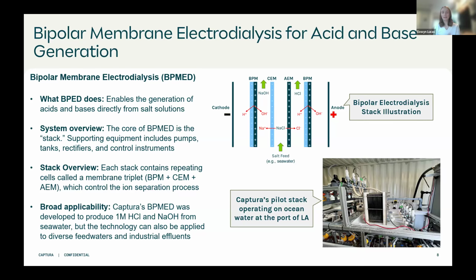So the image on the bottom here is an example of one of our pilot stacks that's currently operating at this Port of LA pilot plant I mentioned. This example has 100 repeating triplets. The dark area that you see in the middle between the two white plates are the gaskets that go in between each layer of membrane to create this repetition. Therefore you minimize the voltage needed for your end reactions across, in this case, 100 different channels of acid and base. So you're able to create more acid and base for a lower energy input need.